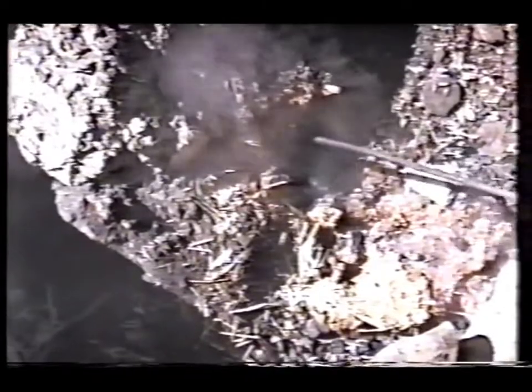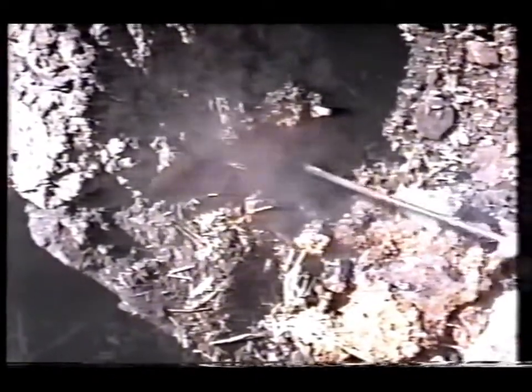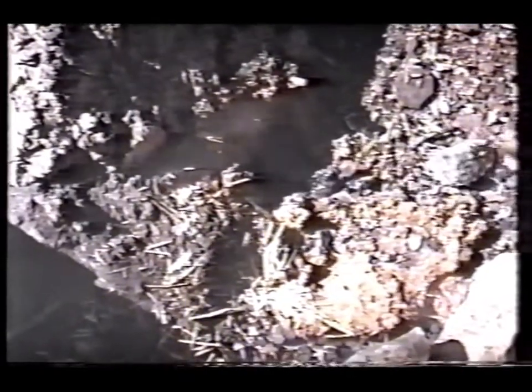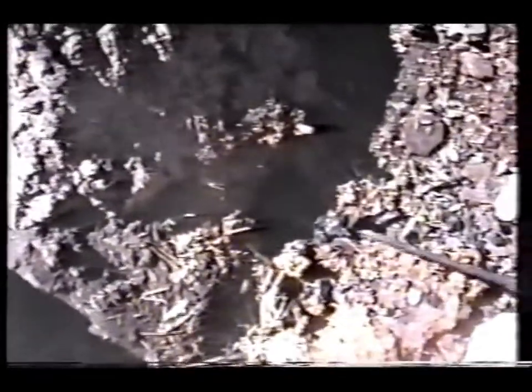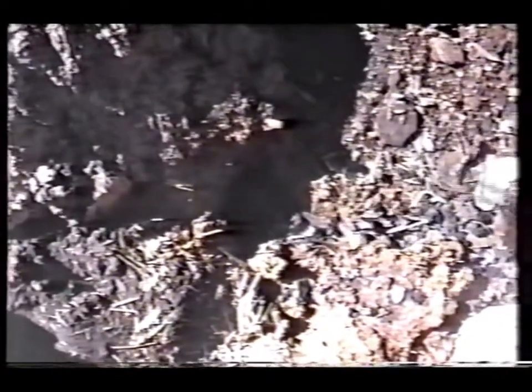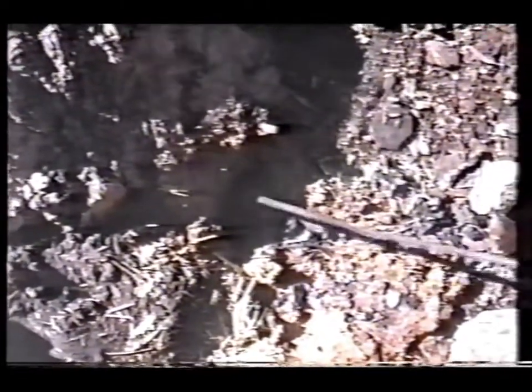Also, the tap hole would be checked towards the end of the smelt to see if any slag was running, which would give the smith an indication of the presence of a bloom. It could often be felt actually by probing through that hole. If you left it open all the time though, you would get a certain amount of leakage of air draft, so it was usually clogged with a rock or some clay. In this case you can see some slag that has actually flowed and then solidified.